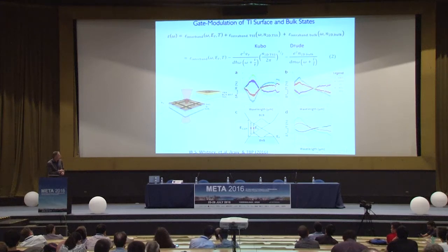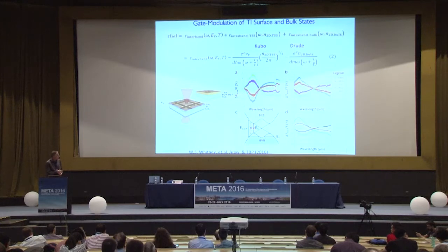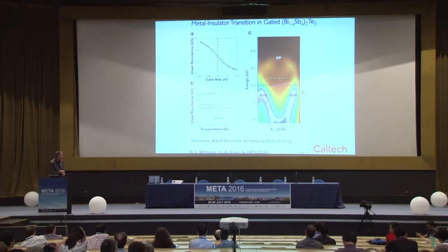And if we look at the infrared optical response, we can see as a function of gate bias evidence of tuning the Fermi level from the Dirac surface cone into the bulk valence band, and a simple model that accounts for the Pauli blocking and band filling that occurs as you deplete the surface state and then the bulk band upon excursion of the Fermi level is nicely in accord with these far infrared experiments. And you can see if we combine this with electrical measurements, transport and Hall effect measurements, we can see evidence that we're electrostatically able to tune the Fermi level from a position where it lies within the Dirac cone into the bulk valence band of the semiconductor.